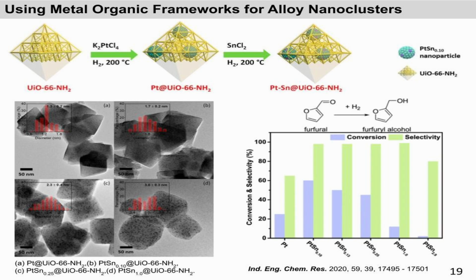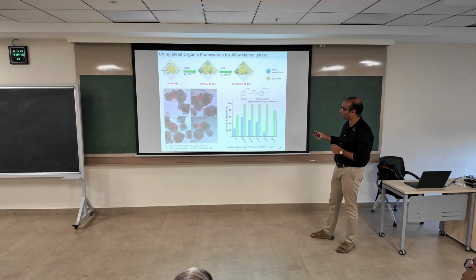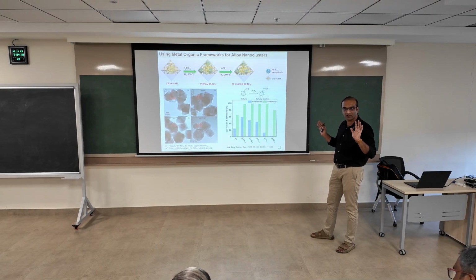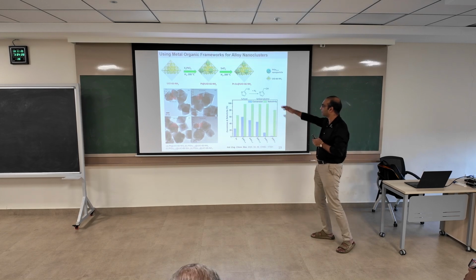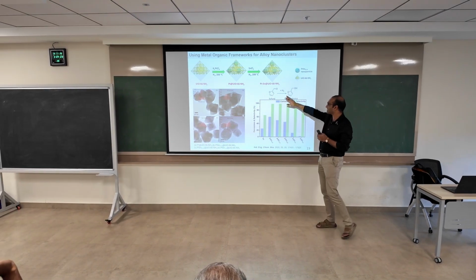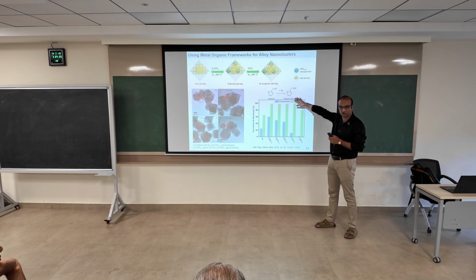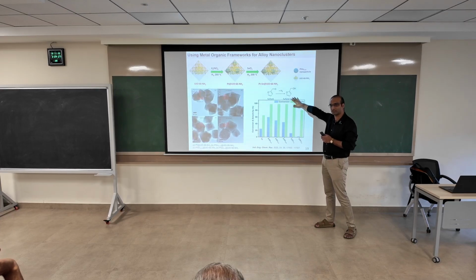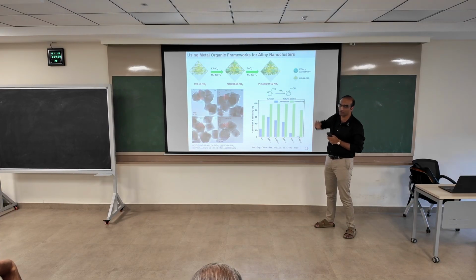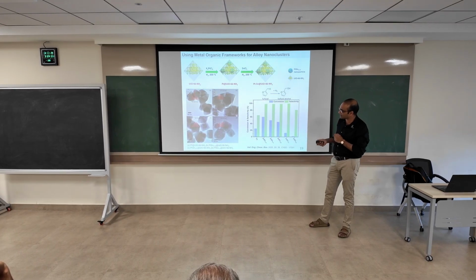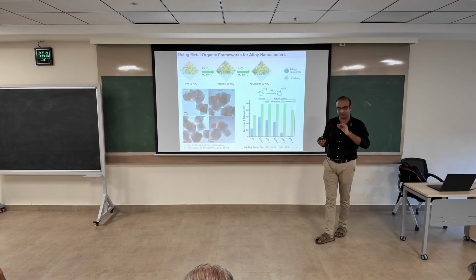On typical platinum, you don't get good selectivity. This compound breaks down into all manner of things. Okay, you'll get CHO, you'll get furan, you'll get all the undesirable things, you won't get furfuryl alcohol. This is also a very important starting material for the organic industries. Here what we did was just include tin. And again, we could control the size to around 1, like here 3 nanometers maximum. Okay, and it was inside the MOF.